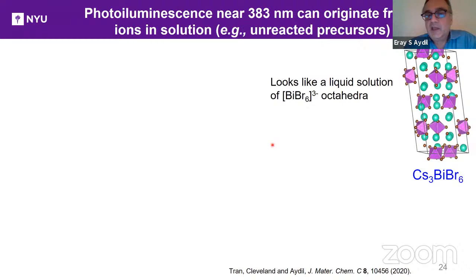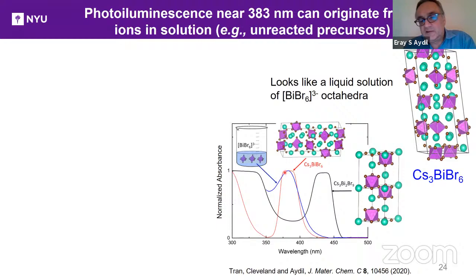Okay, so one of the things that I already pointed out is that this structure looks like a liquid solution of BiBr6 octahedra, right? If I took away these lines that are telling you where the unit cell is, it might as well be a schematic of a liquid solution of BiBr6 that is solvated by the cesium ions. And indeed, here is that solid absorption, and here is the liquid absorption in blue. They're right on top of each other. So these are really acting like isolated octahedra.